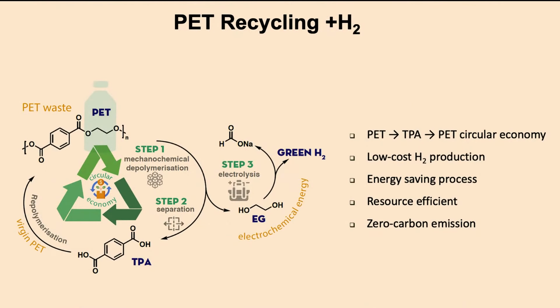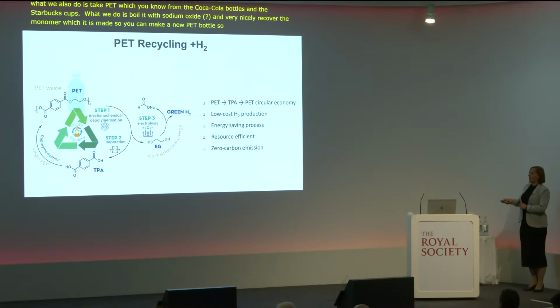And not only that, but what we also do is we take PET. You all know PET from the Coca-Cola bottles and the Starbucks cups. What we do with PET, we ball mill it with some sodium hydroxide, and we can actually very nicely recover the monomer from which PET is made, which is terephthalic acid. So you could make a new PET bottle. So we could have a circular recycling of PET. And on the side you make ethylene glycol.